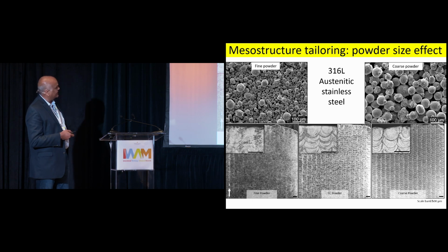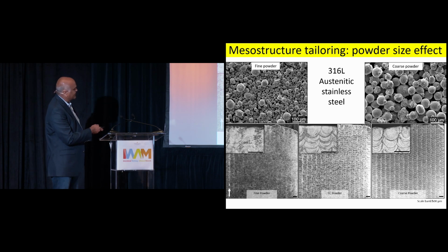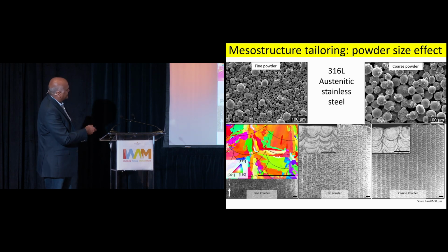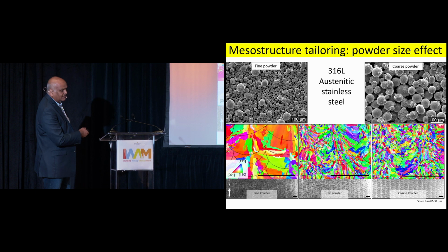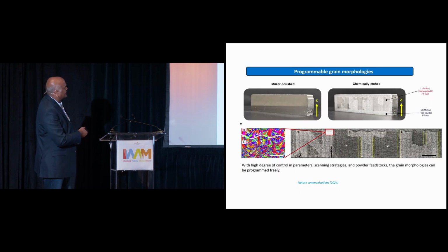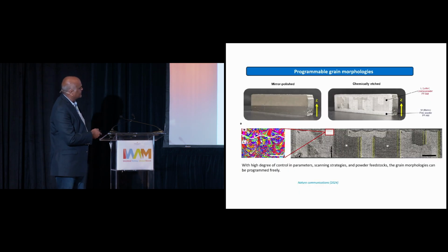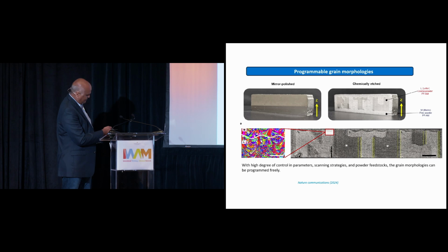Depending on the powders, for example, if you do fine powders versus coarse powders, the scale is similar, but you can see these are much coarser powders. So the meso-structure is hard to see, whereas you can see it very clearly here. And this is a mixture of fine and coarse powders. And even the grain features are very different in these materials, okay? Now, in fact, my former postdoc worked on this, and we published a paper in Nature Communications on this.